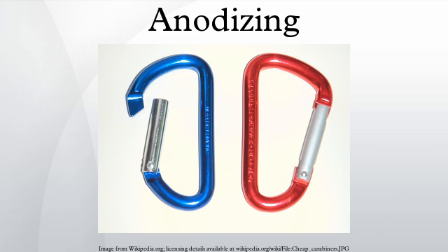Coatings of moderate thickness, 1.8 µm to 25 µm, are known as Type II in North America, as named by MIL-A-8625, while coatings thicker than 25 µm are known as Type III, hardcoat, hard anodizing, or engineered anodizing. Very thin coatings similar to those produced by chromic anodizing are known as Type IIB. Thick coatings require more process control, and are produced in a refrigerated tank near the freezing point of water with higher voltages than the thinner coatings.